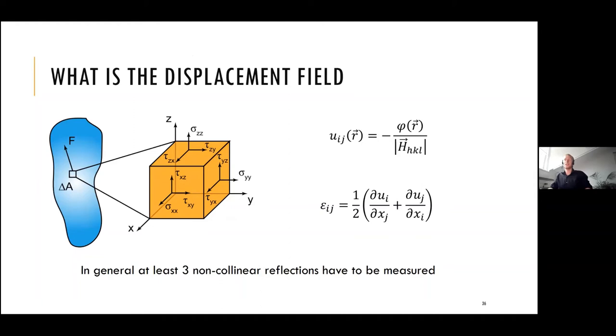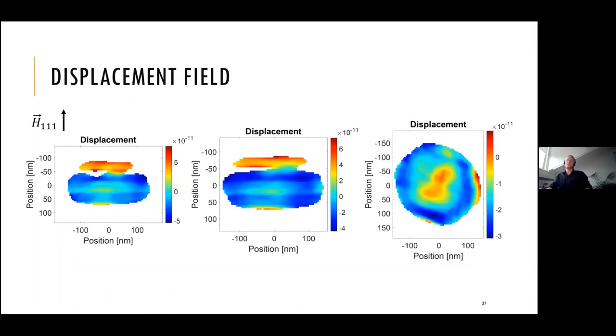So basically we can extract the displacement field from the phase, as it was explained before. And as we know from the elasticity theory, the strain, or the amount of relative distortion of the crystal, can be calculated as a gradient of the displacement field in the respective direction. And if you measure at least three non-collinear reflections from your crystal, you can reconstruct the full tensor of the strain inside. So in this case, this is the displacement, how it looked after the conversion.